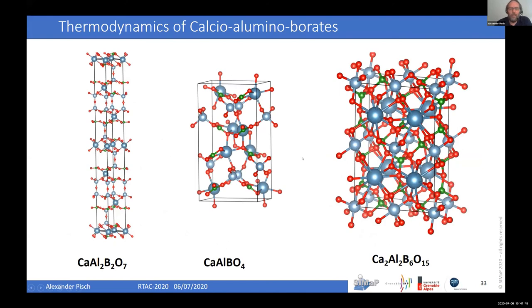So the next example I will give is the lime alumino borate system. In this system, again, not much information in the literature. There is one isothermal section at 800 degrees. And there are three compounds reported in the literature. Two compounds, calcium Al2B2O7 and calcium AlBO4, which are reported in the high temperature isothermal section, and one compound, which is a natural occurring mineral, called johachidolite. It is not available. There's no thermodynamic data available. It's not even in the phase diagram.